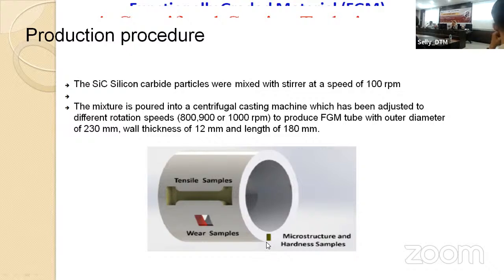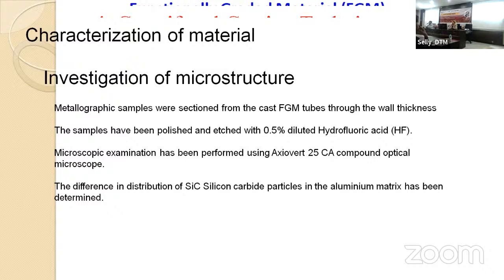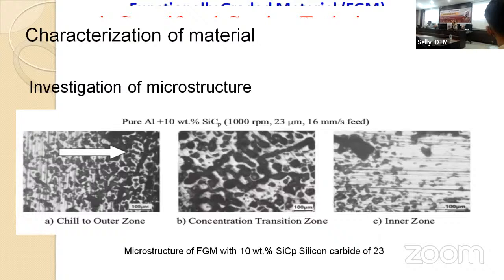Remember that it's 12. And I will show you some mechanical properties changing according to the axis and changing according to the inner and outer direction, of course. These samples were sectioned, first polished, and etched with hydrofluoric acid. And then we use them for microscopic examination, performed with an optical microscope. Generally, I use a light microscope and optical microscope, and we use image processing methods. The differences in the distributions of the silicon carbide particles in the aluminum matrix were analyzed by image processing using the light and optical microscope.